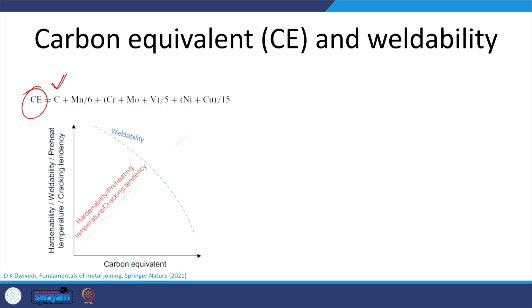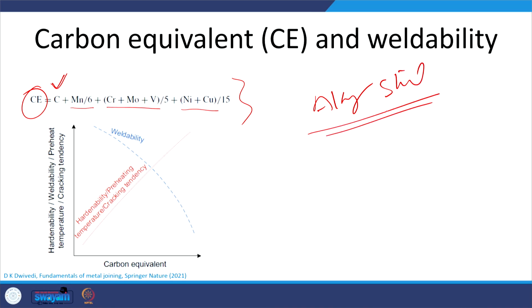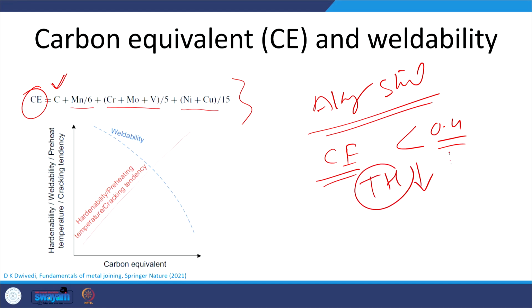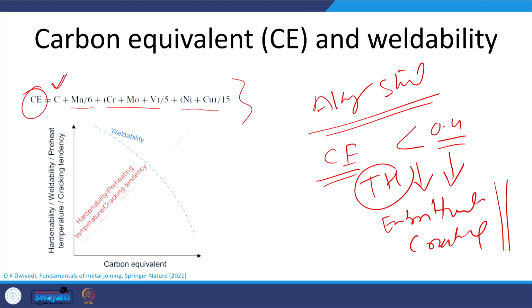If we have to calculate the CE, carbon equivalent, then we add the carbon weight percentage directly, then Mn, manganese, is divided by 6, chromium, molybdenum, vanadium are divided by 5, and nickel plus copper is divided by 15. Depending upon the alloying elements present in the steel, this equation is used for determining the carbon equivalent of alloy steels. If the carbon equivalent of the alloy steel is less than 0.4, the transformation hardening tendency will be very low, and therefore the issues related with transformation hardening, like embrittlement and cracking of the weld and HAZ, will be limited. Therefore, if we have a lower carbon equivalent, then the weldability is high.